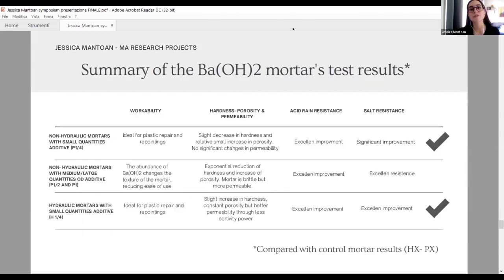That is the summary of the result of all my tests, and we can see that overall, mortar containing a smaller quantity of barium hydroxide were the ones that had the better overall results. So the results are ideal for the workability, hardness, porosity, and permeability remain the same or increase with respect to mortar not containing barium hydroxide, and the resistance to acid rain and salt increases a lot.